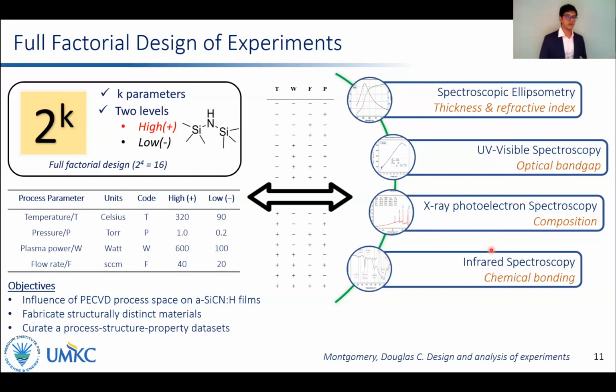Here I'm going to highlight a few key results. We employed full factorial design of experiments in which each PECVD parameter - temperature, pressure, power, and flow rate - was considered at 2 levels, high and low, representing reasonable extremes compared to literature values. The advantage of factorial design is that it considers all 16 possible combinations, because with 4 variables, it leads to 2 to the power 4, or 16 different combinations of these parameters.